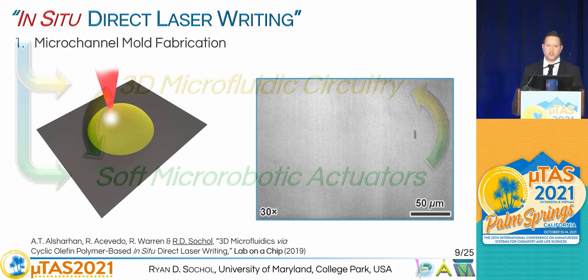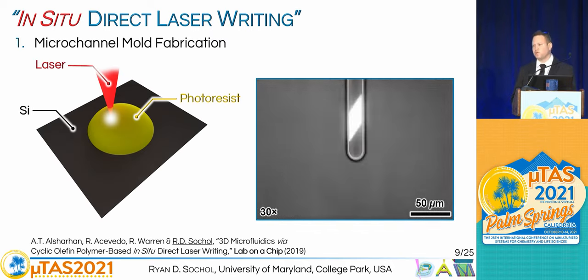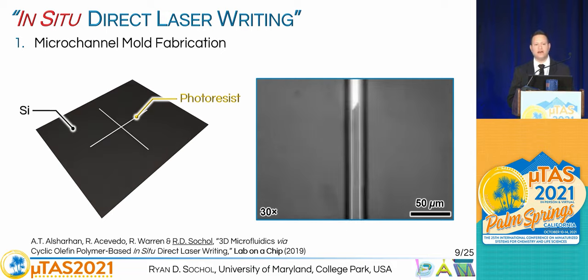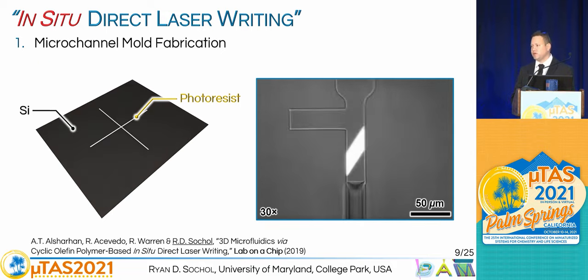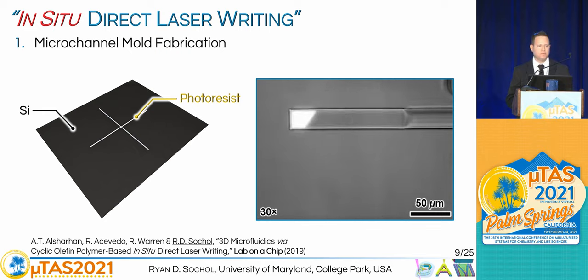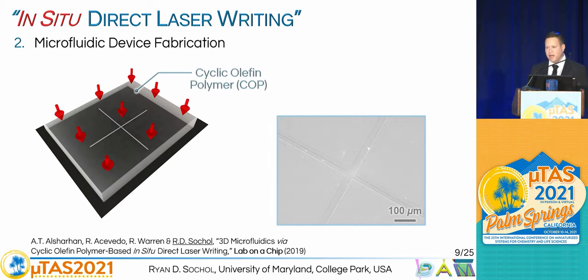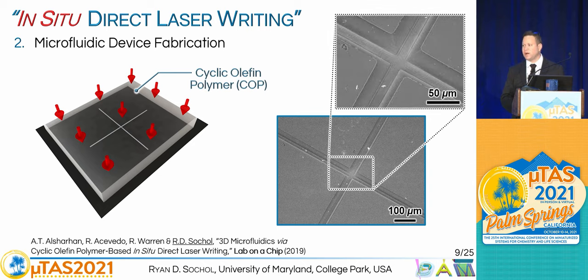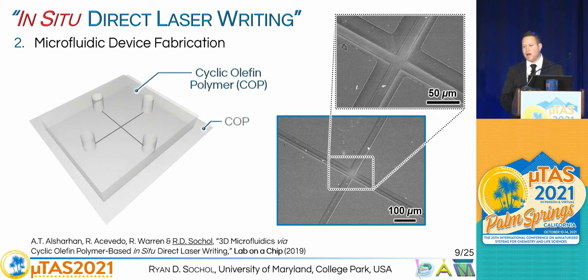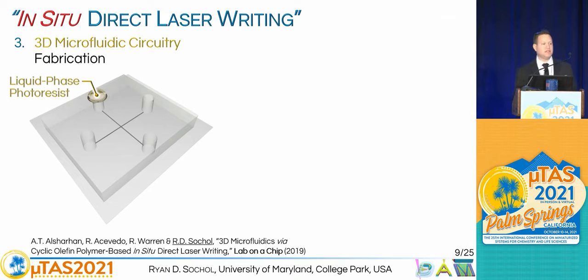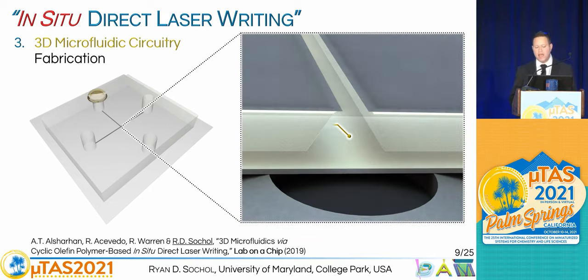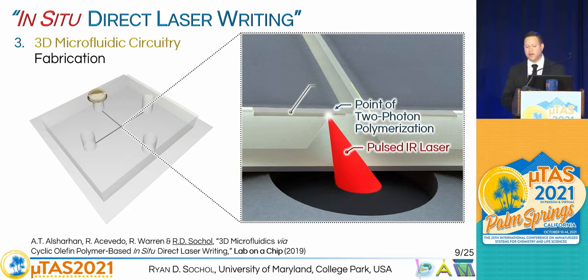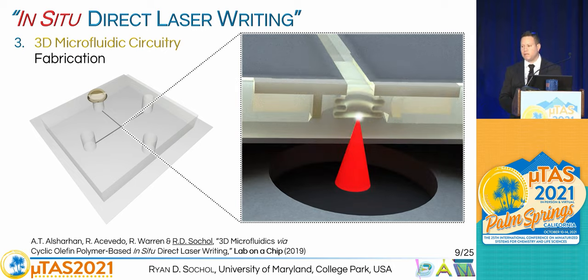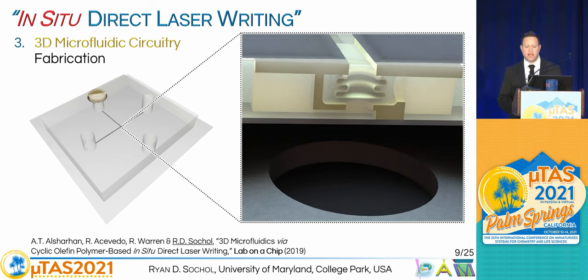So the overall manufacturing strategy has three steps. First, we're using direct laser writing outside of a chip, and we're just printing the microchannel mold directly onto a silicon wafer. Next, we're going to be taking a thermoplastic, and we're going to be thermally embossing it in order to replicate these channels, and then we're going to bond it to have a fully enclosed microfluidic system. And then the last step is basically to infuse a photoreactive material into the microchannel itself. And then we're able to scan this laser point by point to cure the material to be able to build up these more complex three-dimensional structures at these scales.